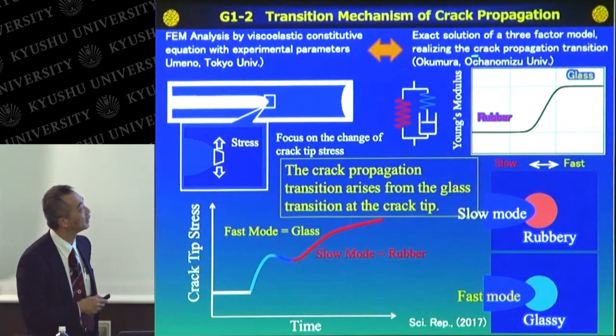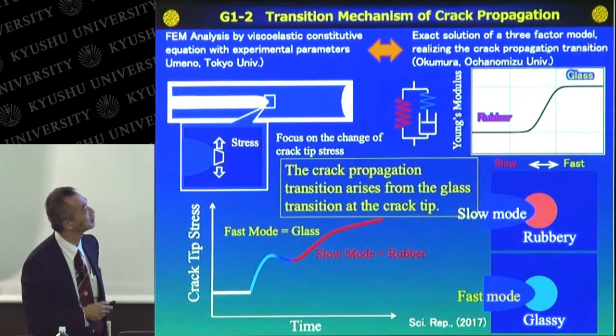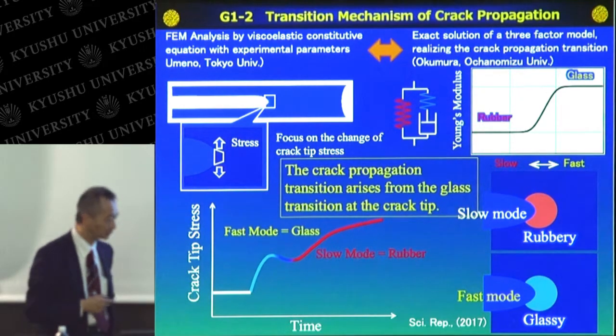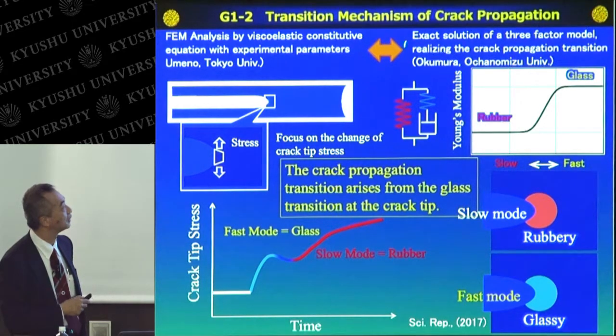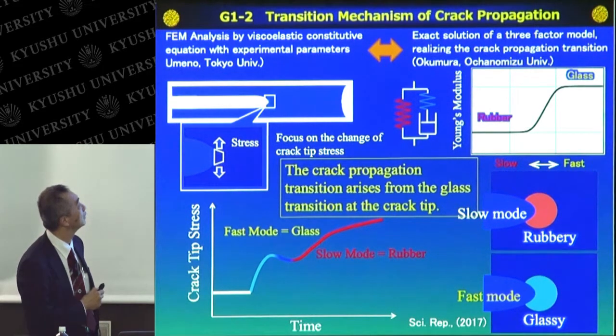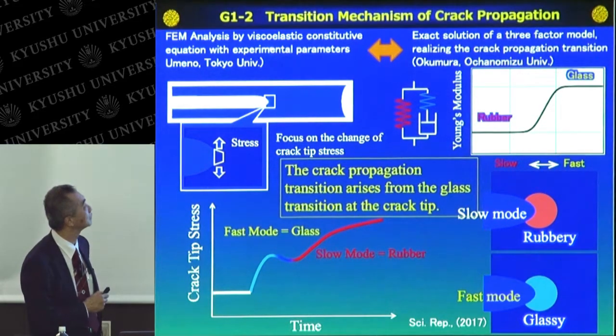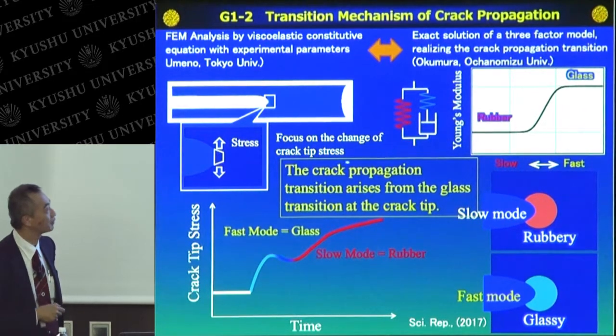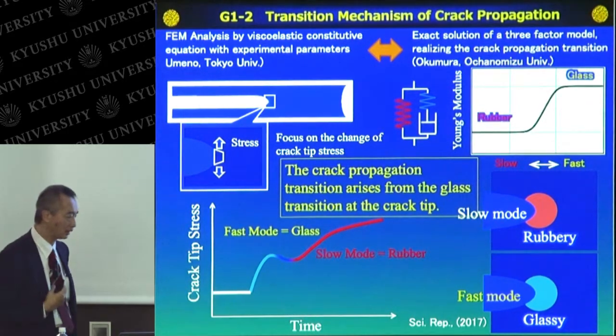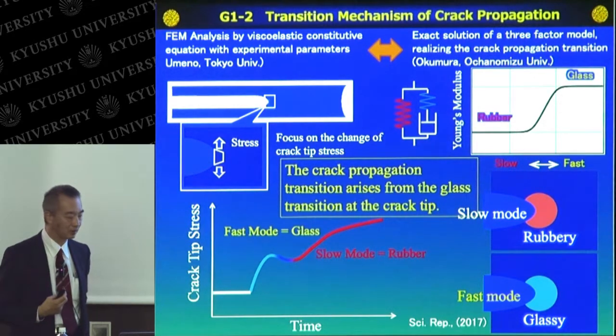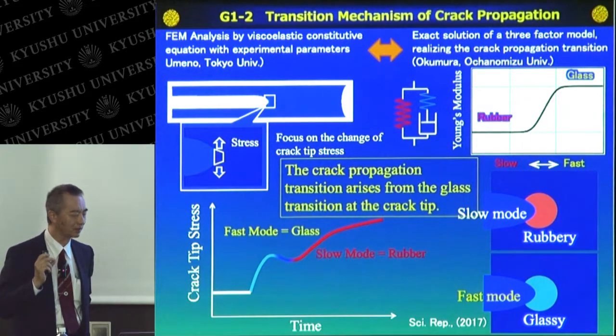In this case, Professor Okumura at Ochanomizu University found the exact solution of the three-factor model realizing the crack propagation transition. This is the first finding of an exact solution in the field of crack propagation. And also Professor Umeno at Tokyo University performed FEM analysis by a viscoelastic constitutive equation with experimental parameters. And so finally, the crack propagation transition arises from the glass transition at the crack tips. So this finding leads to the development of a very thin, tough tire by Bridgestone.